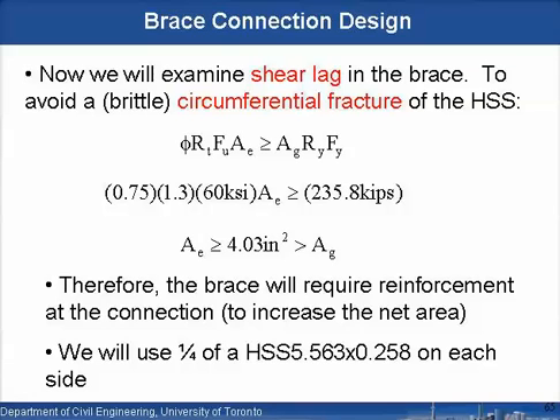So we can solve for the effective area required, A sub E, and we get 4.03 square inches. Now, that means that at that critical cross-section where we've got that little slot, we need an effective net area which is actually greater than the gross area. The gross area of the tube is only 4.01 square inches. So we need a cross-sectional area to avoid this failure mode which exceeds the gross area of the tube. Problem. So we've obviously got to put some sort of reinforcement in.